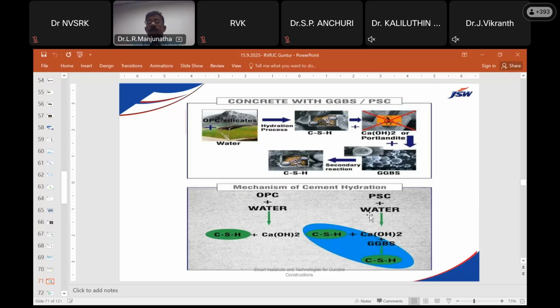So what GGBS or slag will do is react with calcium hydroxide and convert it into CSH gel again. The interfacial transition zone, that is nothing but the space between the cement paste and aggregates, is always weak. So by adding this fine material, GGBS, which is finer than cement, we are filling the voids, and a secondary reaction takes place, bonding the particles together. So the bond strength will increase.